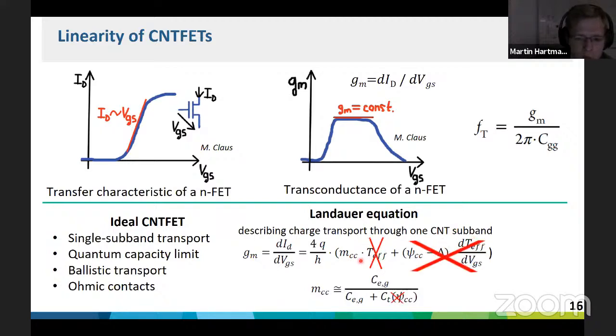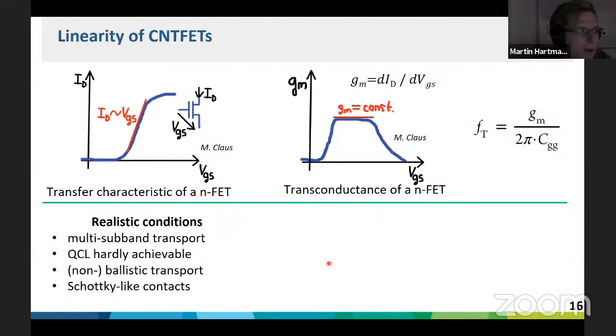This T becomes 1. And then furthermore, when you're in the quantum capacitance limit, it means that you don't have any tube charge and no related tube capacitance. That means that the scaling factor M becomes 1. And then finally, your GM is only proportional to the electrical charge and the Planck constant. And this gives rise to the prospected higher linearity. But in reality, it's not like that.